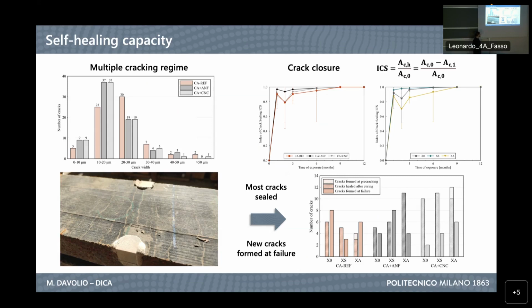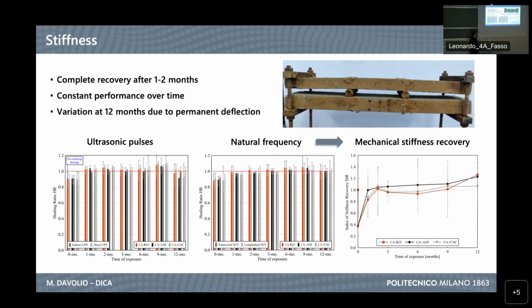And also, the cracks we formed at pre-cracking and that were sealed remained closed even during the failure test, which localized the failure on new cracks, meaning that the products developed during the sealing process were effective to bridge and to close the cracks, also resisting from a mechanical point of view. The stiffness was addressed both from the dynamic modulus, or recovery of the dynamic modulus compared to the initial condition and the damage we applied to the specimen, and this confirmed what we observed from the crack sealing.